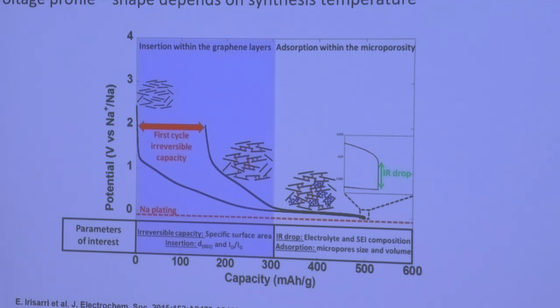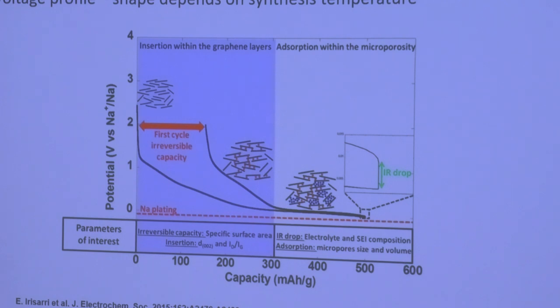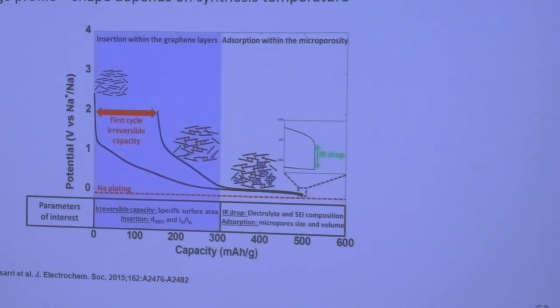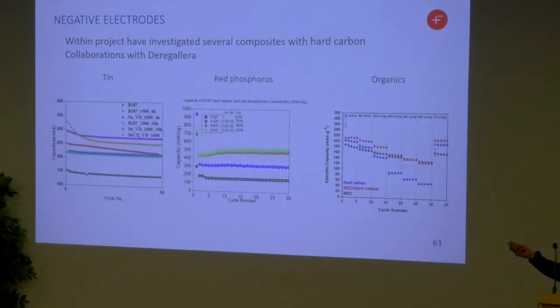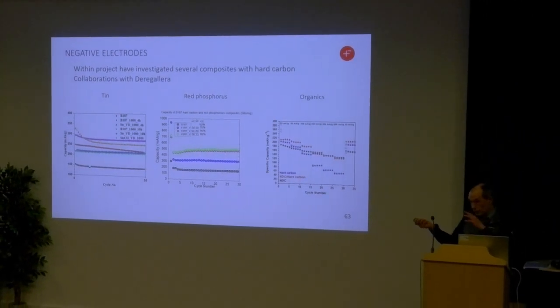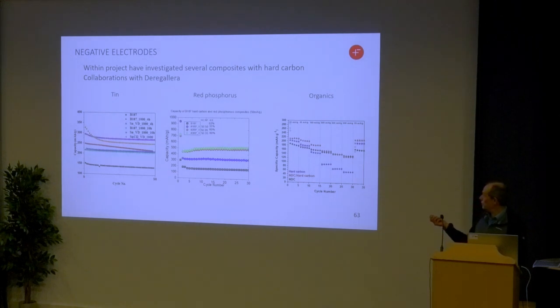The new development that Tom was mentioning at the beginning concerns hard carbon, and in fact extending this plateau bit hugely by producing porosity using zinc and getting much higher capacities. In the project we're doing composites again, composites with tin, which may actually be doing some of the similar stuff to what zinc does in this new paper. Composites with phosphorus, and I'm doing some work with organic based materials, which have the advantage that you can tune them a lot, but the disadvantage is that they're lousy conductors of electricity. So to get around that, we use carbon to make things more conducting. What happens if we mix hard carbon with an organic? And actually we get something that works really well, better than either of them. So the idea works.